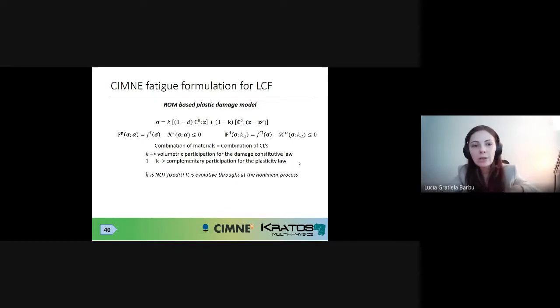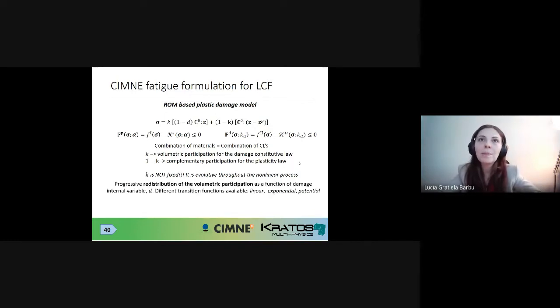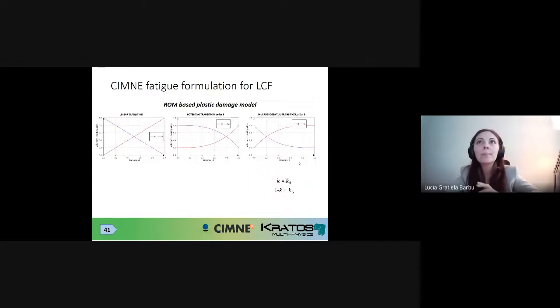So if you have a material which starts to exhibit plasticity at the beginning of the nonlinear process, but later on migrates into a damage behavior, or a combination of these two, this model is perfectly capable of capturing this. This is a very, very important characteristic. When we are dealing with progressive redistribution of the volumetric participation as a function of this damage internal variable, we have proposed different transition functions available: linear, exponential, and potential. And here you can see the variation of the damage and plasticity participation.